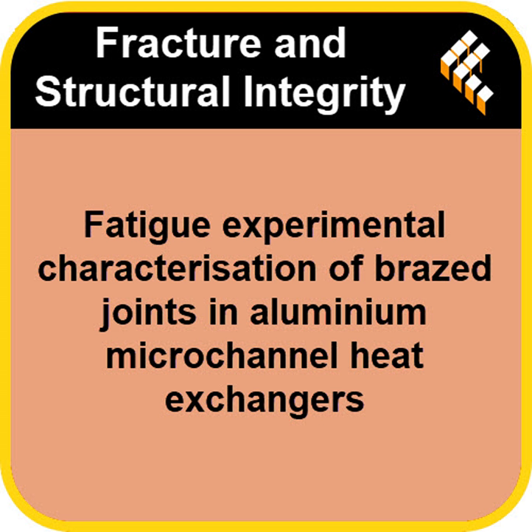And what did the chemical analysis reveal? What were these tiny flaws made of? The analysis showed they contained fluorine, F, potassium, K, aluminium, Al, and also cesium, Cs. Fluorine, potassium, aluminum, cesium.